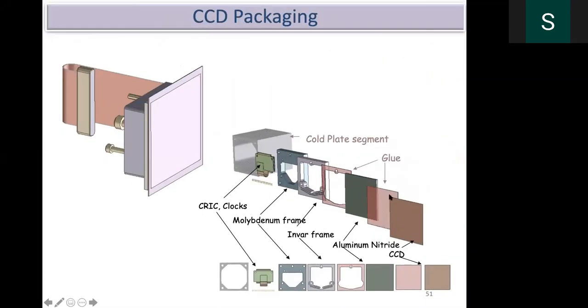See here, aluminum nitride is grown. This is a CCD packaging. Different materials are there, like molybdenum frame and Invar frame. One particular layer is aluminum nitride. This is because it will act as a heat sink. So that is the reason aluminum nitride is a very important material, not only as an insulator, but also as a thermal conducting layer.